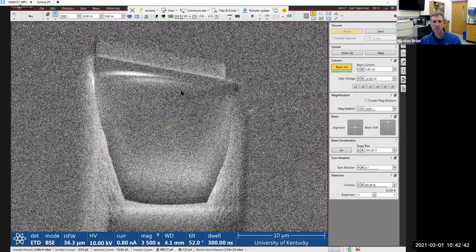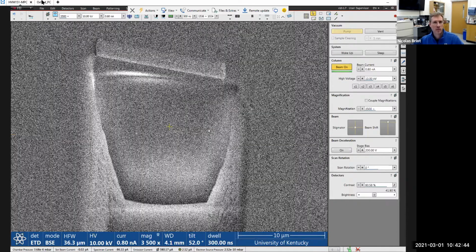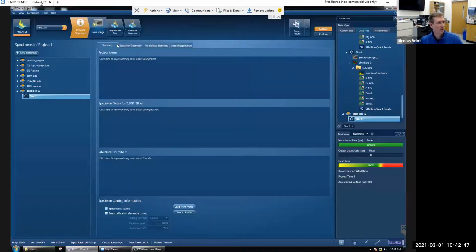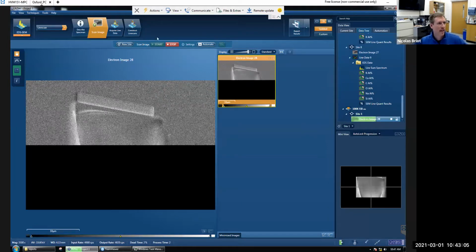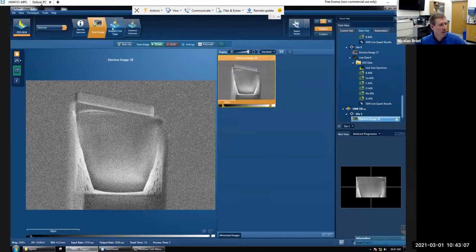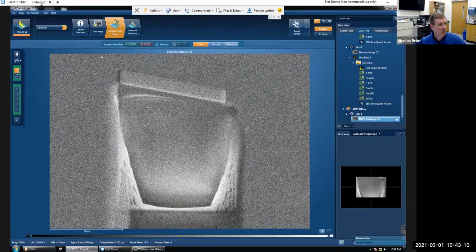Okay, something like that. So if I go back to the PC here and do the drift correction, I think it's going to help. Grab the image and do the line scan. The glass doesn't cut as fast as I was hoping. I mean, I asked for 30 microns, but everything is calibrated for silicon, not silicon oxide. So it doesn't cut as deep, but we should still have like over 10 microns. So hopefully it works well.